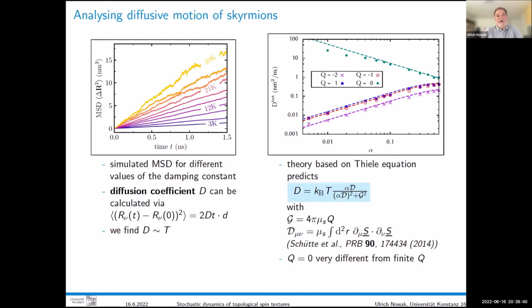And that comes along with the damping constant. So you could say alpha D here is a measure of the dissipation, and G is a measure of the topological charge. And the interesting point here is that there's a big difference whether G is finite or not. Because if G is 0, then you get a 1 over alpha. And if G is finite, then you get an alpha dependence. And that's what you see here. So that means the diffusive behavior of the spin textures depends on the topological charge. And Q equals 0 is an exception. So topologically trivial is very different, 1 over alpha, from topologically non-trivial textures, which have a finite Q.